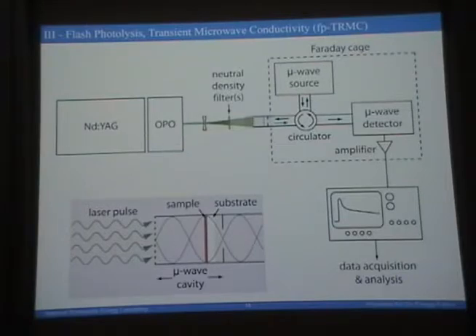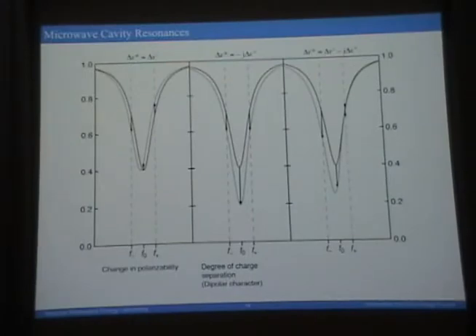So the nice thing about this technique is you can probe the real and the imaginary part of the dielectric constant of the sample. And it's the imaginary part of the dielectric constant that turns into photoconductivity, and it's photoconductivity that's giving you the signal from free carriers.